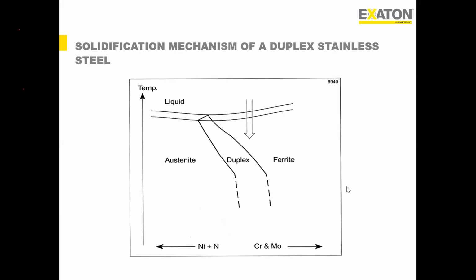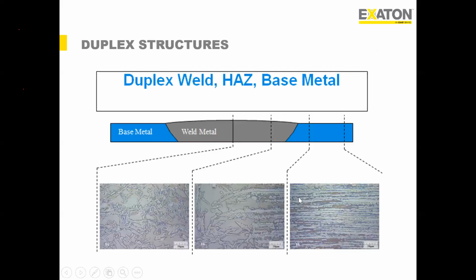So this is a typical microstructure of a duplex material. This is the base material structure. This particular microstructure you can see is the HAZ, and this is the weld metal structure. The weld metal is a cast structure, whereas in the base material the grain orientations are much more systematic compared to the weld metal and heat affected zone.